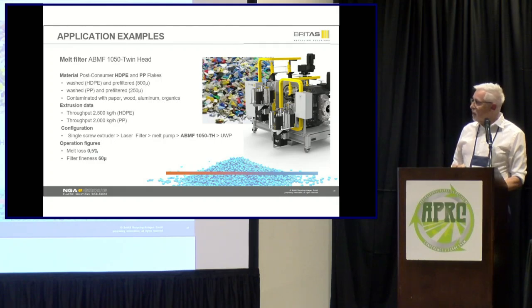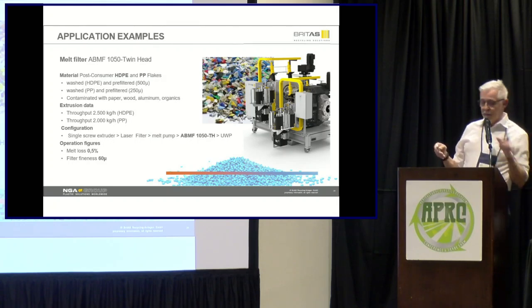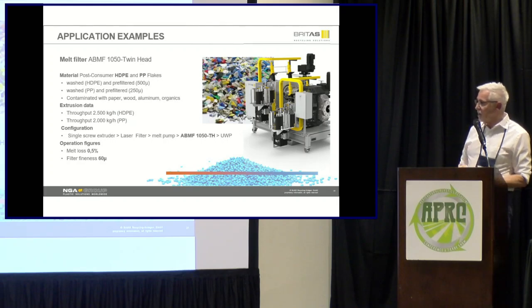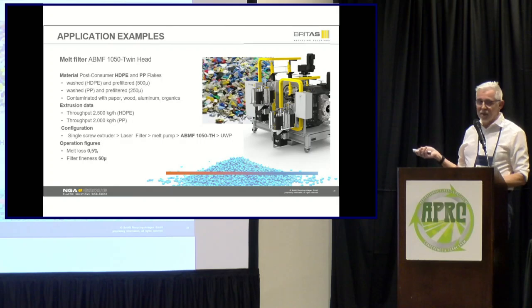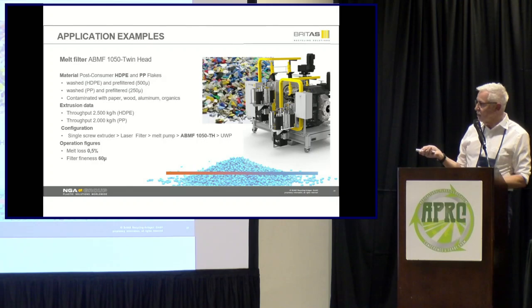Or as well a twin head with single screw with a laser filter. And as a second stage, the twin head and the underwater pelletizing system. Filter fineness is 60 microns and melt loss is 0.5%. And melt loss at the end is money, because the melt loss you pour on the floor.